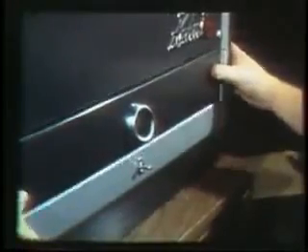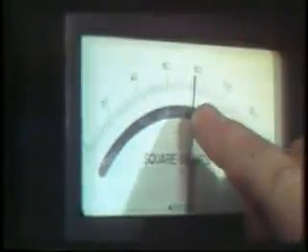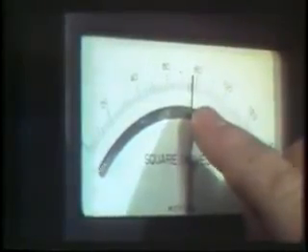It is necessary to know the number of square inches of surface to be plated in order that the proper plating current may be chosen. Light transmitted by the photographic positive and picked up by a photoelectric scanner gives an accurate indication of the area of the resist. A calculation will determine the current required.